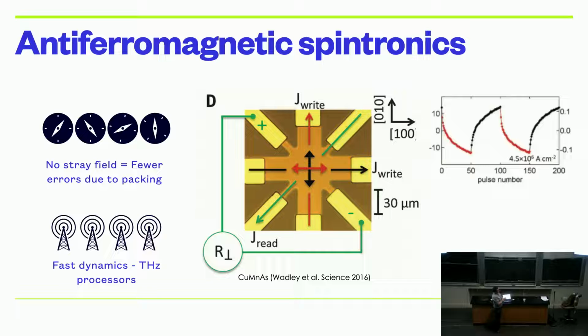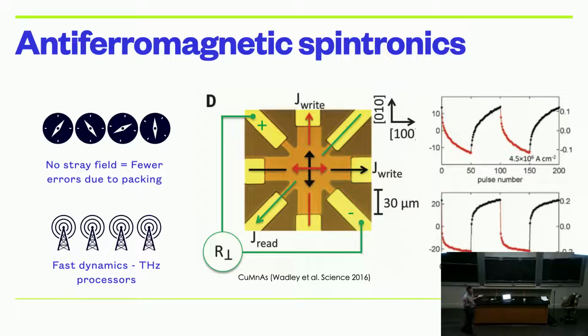So when you're flooding the current north to south, you get a decrease in the resistance. This is a pulse in the north-south direction, like 50 pulses, and you get here. And then you pulse it in the perpendicular direction, east to west, and your resistance goes in the opposite direction. So what they were trying to demonstrate is that this is a kind of memory: pulsing the current in this direction gives you low resistance, pulsing the current in this direction gives you a high resistance. So it is a kind of memory, I can see that. Okay, interesting. How does it work? Why does it work?